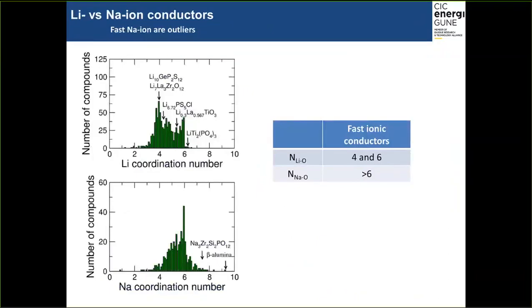So what we found is that fast lithium ion conductors have the typical coordination number of lithium compounds, between 4, like for example for lithium garnet, argyrodite, and 6 for perovskites and NASICON. However, the best two sodium ion conductors, NASICON and beta alumina, have much larger coordination numbers than the usual values found for sodium compounds. I will come back to this later in the conclusions part.